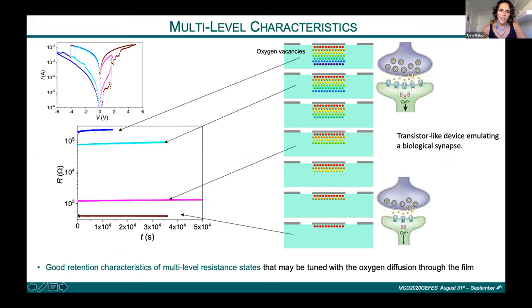Also, we have tested the retention of the states. We have performed different minor loops going to different voltages, 2 volts, 6 volts, and -2, -6. And we obtain different levels of the resistance, and we have tested the stability of the resistance as a function of time. We observe a good retention of the different states.